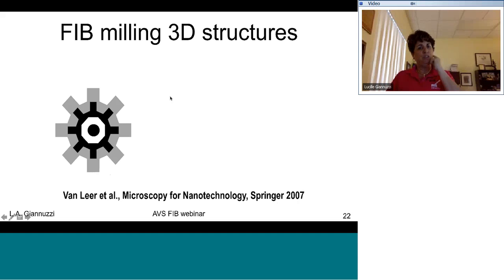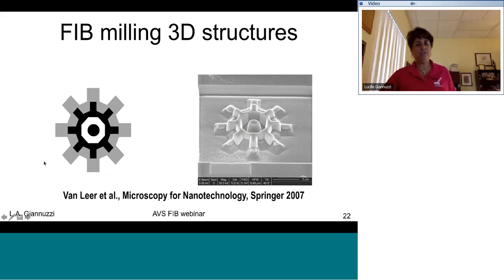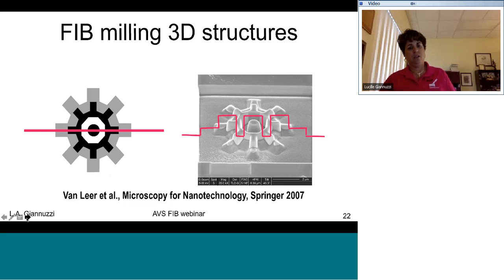So FIB milling of 3D structures becomes really easy if you define bitmap files, for example, where you can predefine what the dwell time is based on a certain grayscale level. So in here we've just got 3 different grayscale levels: white, black, and gray. By FIB milling that, we can immediately generate a 3D structure where the dwell time for each of these different grayscale values corresponds accordingly. So here, if we draw a line across there, we can see that the white area is the largest dwell, the gray is some intermediate, and the black is no dwell at all.